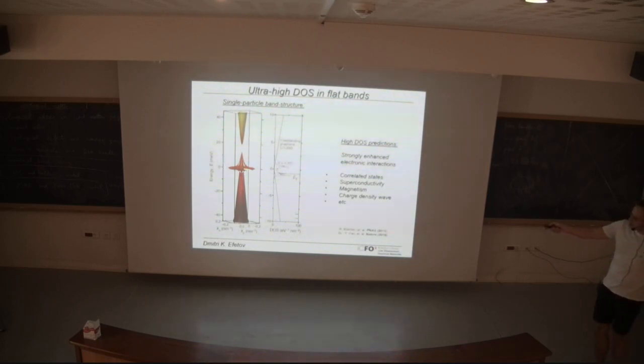And of course, because the bands are so flat, the density of states in these bands becomes extremely large. If I compare the density of states as a function of energy just along this line, you can see that the density of states becomes more than 1,000 times larger than the density of states in normal graphene. So this sort of twist completely renormalizes the band structure, and we end up with an entirely different system from graphene, where the bands are several orders of magnitude narrower, and the density of states is also more than 1,000 times higher.